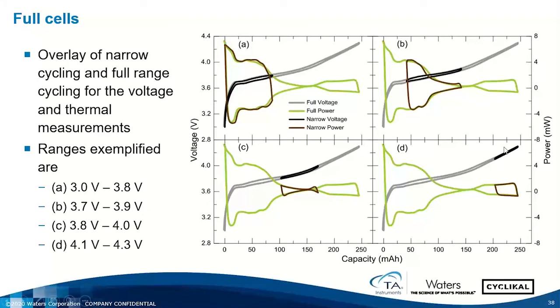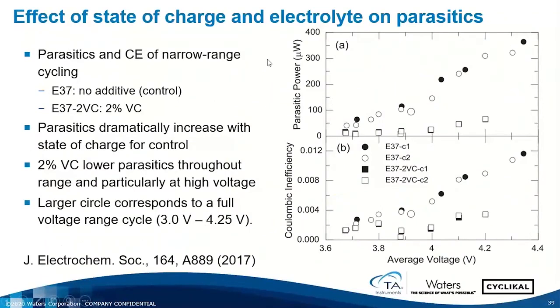Okay, so we take that data and plot it out in a parasitic thermal power format. We get the results shown here. There are two different electrolytes I'm showing results from. One is a base electrolyte, which is 3 parts ethylene carbonate and 7 parts ethyl methyl carbonate. The other is that same base electrolyte, but with 2 weight % vinylene carbonate added.